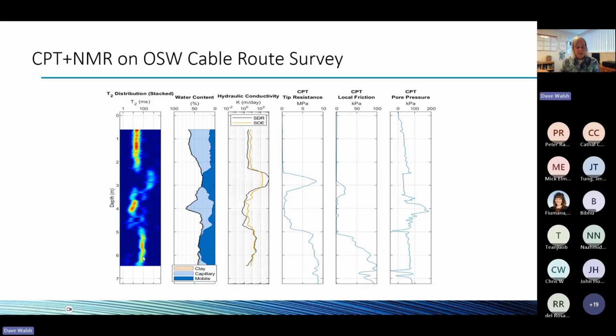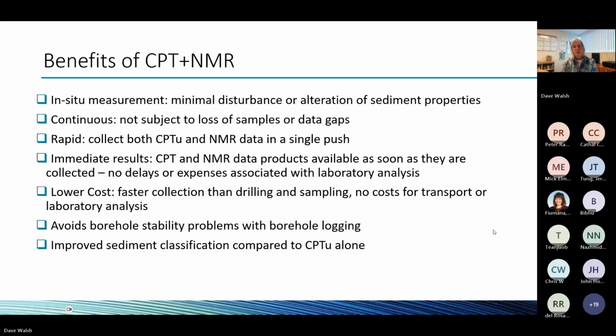And even down here, you see that it's mostly sand in this lower section where things get a little confusing with the CPT. Mostly sand, but there are some fines mixed in. And so it's shown clearly in the NMR data. In fact, you can tell what the fraction of the fine pore sizes are compared to the coarse-grained pore sizes.